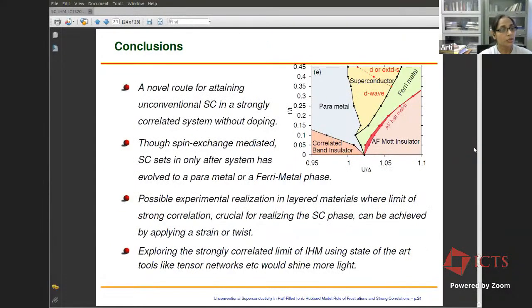So with this, I would like to conclude. Basically, I have talked about a simple variant of the Hubbard model, where just by inducing a staggered potential and taking a very special limit of strong correlation, where the electron-electron interaction as well as the staggered potential are much larger than the hoppings in the system, it's possible to induce superconductivity even at half filling, provided the system has enough frustration against the magnetic order.